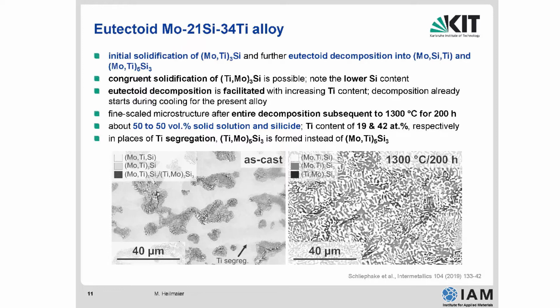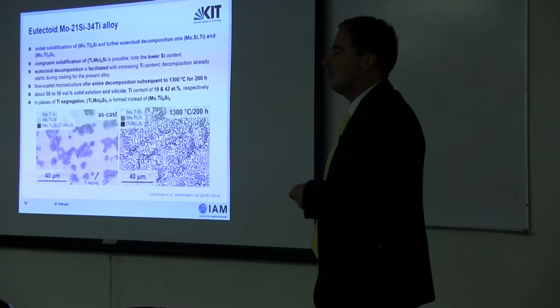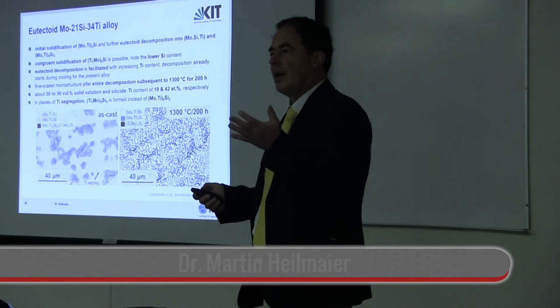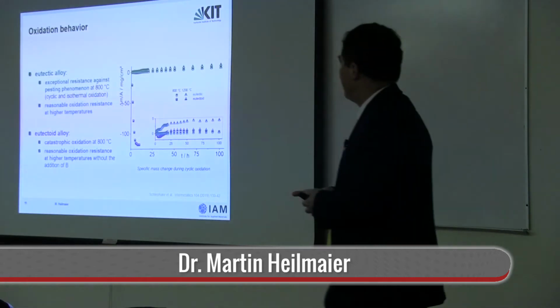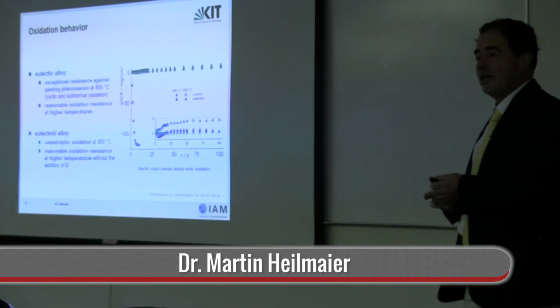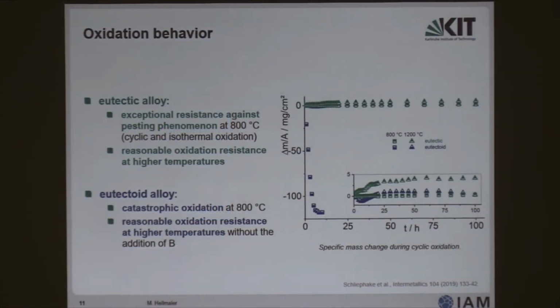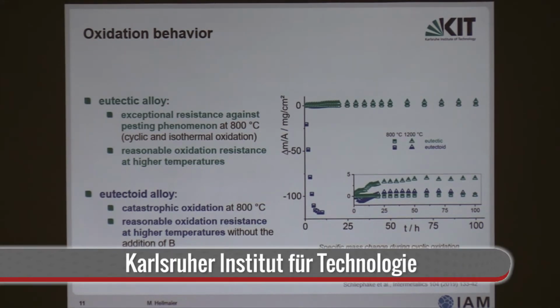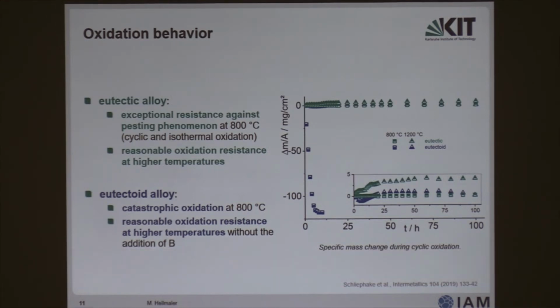Okay. So what you also can see here is that we have a mixture of about 50 to 50 volume percent solid solution and silicide. So this material is a kind of a microcomposite, if you wish. Okay? Now, first I talk about oxidation, then I talk about creep. Oxidation is a major issue for these alloys because assume you have a metallic material, you put it in a furnace, and then you let it oxidize. The furnace operates like an aero engine without the centrifugal forces. So the metal is transformed into oxide. If all the metal is eaten up by forming oxides, you have a brittle material and your engine fails. So this should not occur.